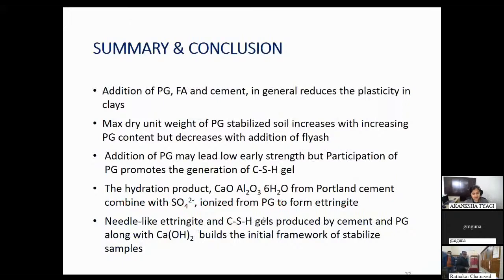So in summary, what I presented today is the addition of phosphogypsum, fly ash, and cement. Basically, it was shown that it reduces the plasticity in clays and brings improvement in clay type of soils. The maximum dry unit weight of phosphogypsum stabilized soil increases, but when you only add fly ash, it tends to decrease. The addition of phosphogypsum may lead to low early strength, because it prolongs the setting time of the cement, but the participation of phosphogypsum promotes the generation of the CSH gel. So in the long term, you will get high strength.